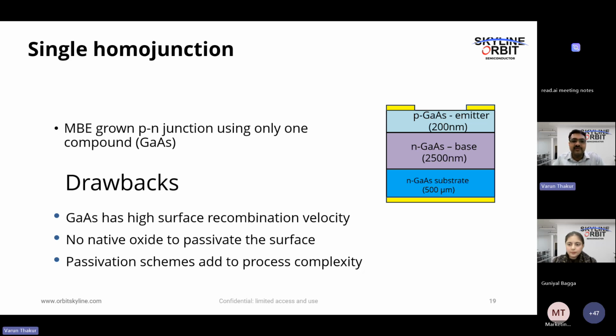But here the problem is that we cannot use the single homojunction because there are a lot of drawbacks. Gallium arsenide has a very high surface recombination velocity. There is no native oxide, like in silicon, to passivate the surface. And we need to add passivation schemes to make this workable, which will add to the process complexity. So since we are anyway going to make it complex, we will not use a homojunction. We will go to a heterojunction.